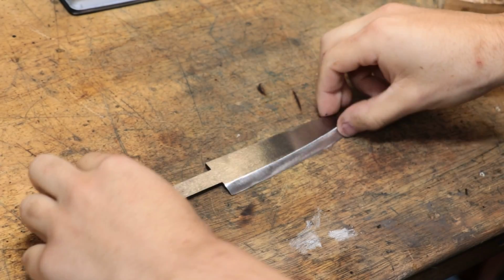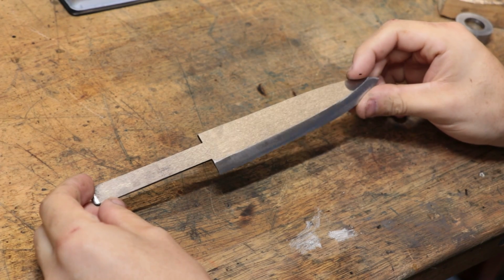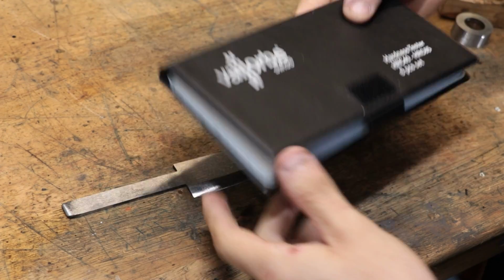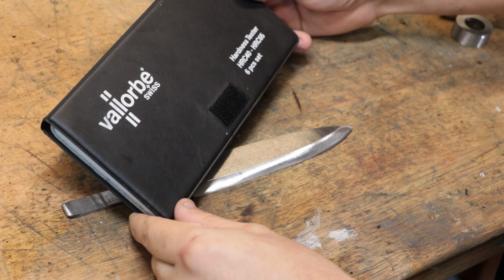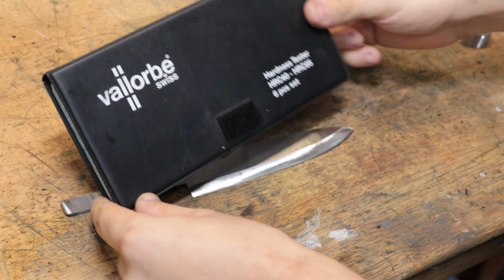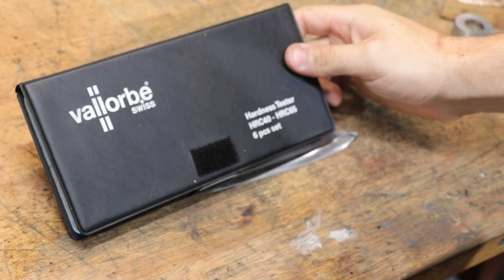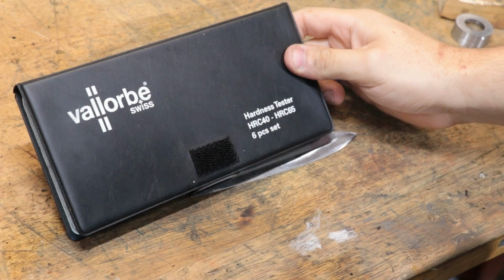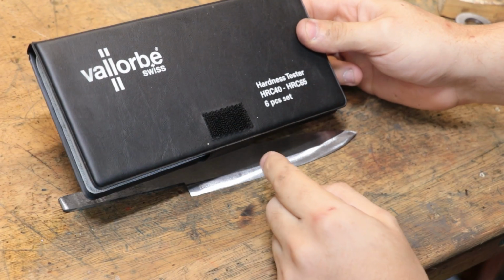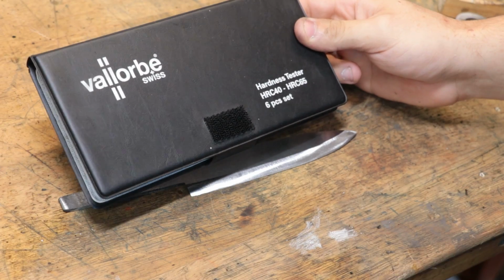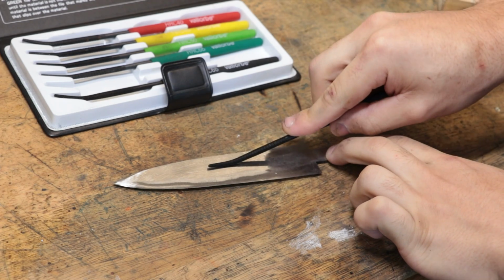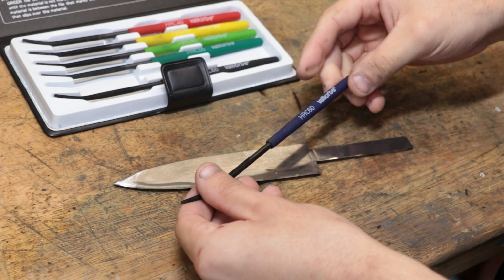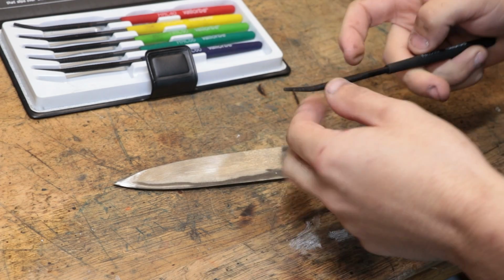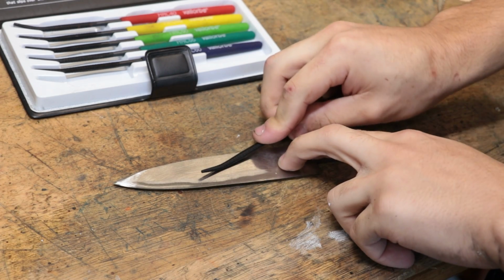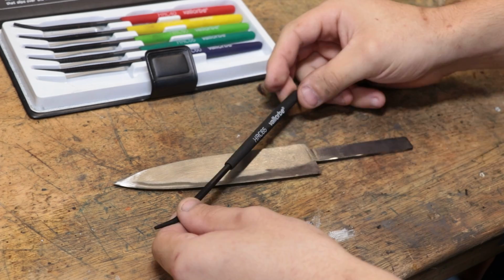Now the final hardness we're left with is just shy of 65 Rockwell C hardness. There are quite a few hardness testing tools which you can buy, and they can get you a very accurate reading on how hard something is, but I think for a home workshop, using these hardness testing files should be good enough. As per the files, the 60 Rockwell C hardness file doesn't bite, but the 65 is only just starting to, so the hardness is just below 65 Rockwell C.